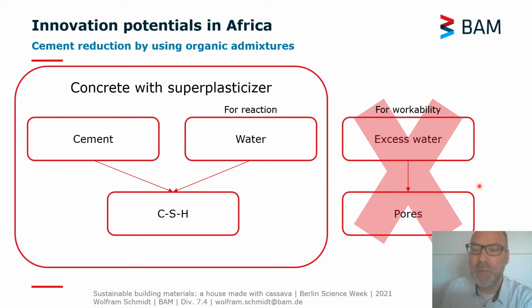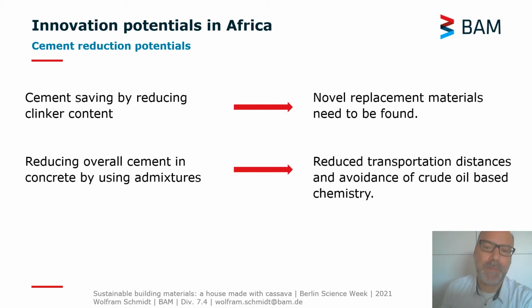Now, if we are using superplasticizers, they adsorb on the surfaces of particles and increase the workability without adding water, so we do not need excess water. And with these superplasticizers, we can really increase the strength, and by increasing the strength, we can reduce the overall cement amount that would be required. So both work in parallel. We've got these two strategies.